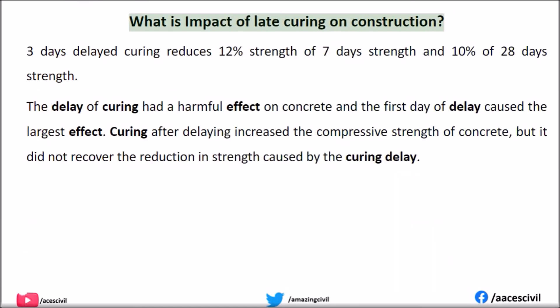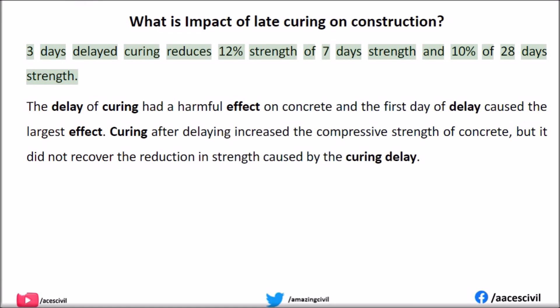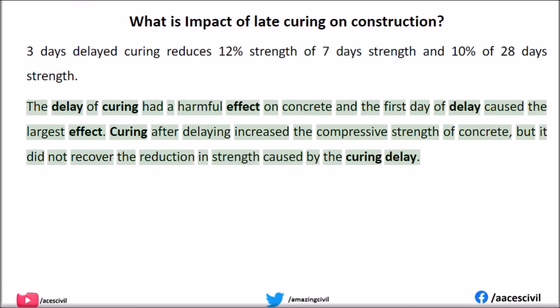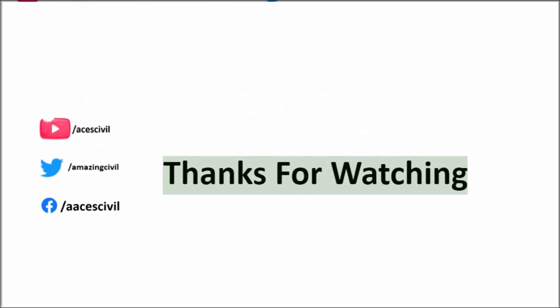What is the impact of late curing on construction? A 3-day delayed curing reduces 12% of the 7-day strength and 10% of the 28-day strength. The delay of curing has a harmful effect on concrete, and the first day of delay causes the largest effect. Curing after a delay does increase the compressive strength of concrete, but it does not recover the reduction in strength caused by the curing delay.